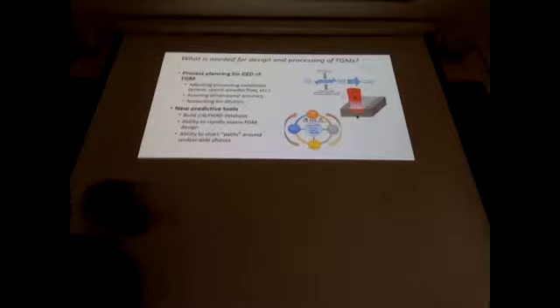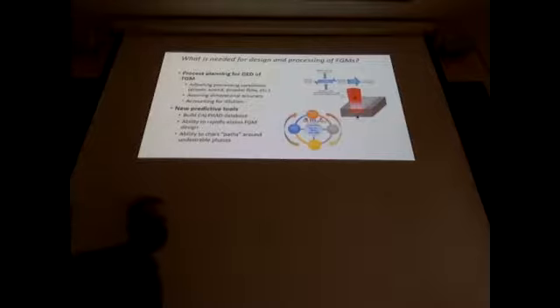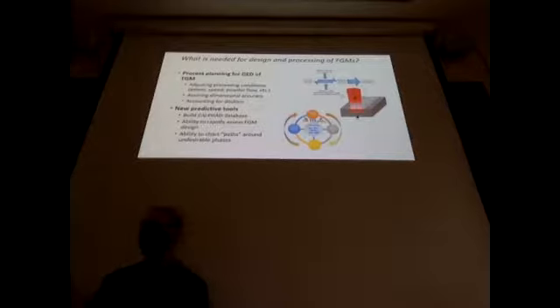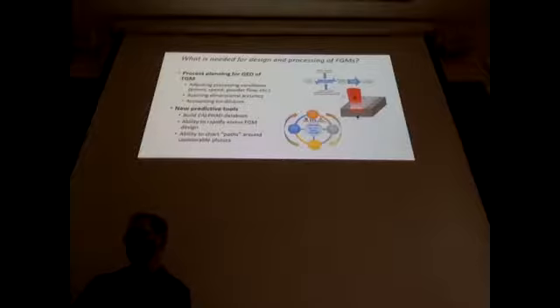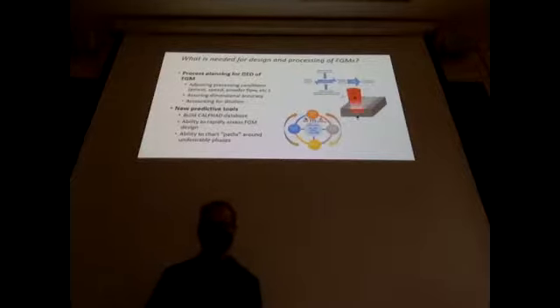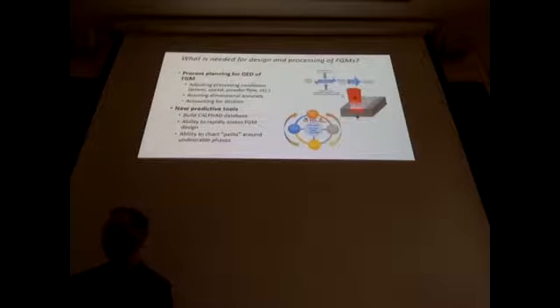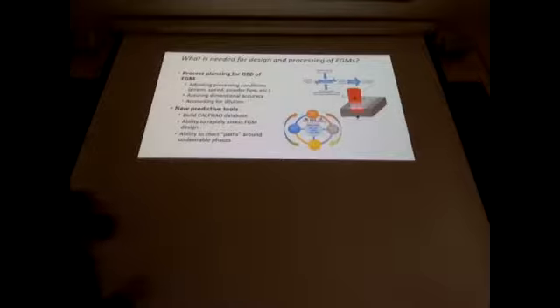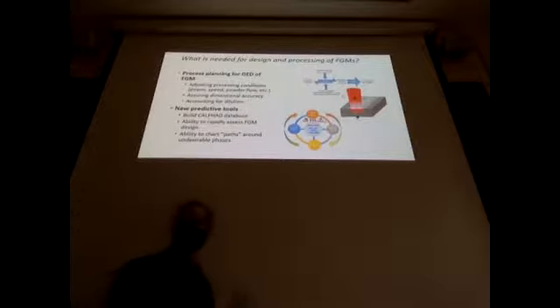And one of the 2 areas that came up that we really felt like we needed was process planning for DED of functionally graded materials. Basically, you're asking to change the material on the fly. And the benefit of additive manufacturing is you can do this layer by layer. You can design where you're putting your material down, and that in turn can design where your grading goes. But in order to do that, you need to make sure that the laser system and the power delivery system is able to compensate for these changing material types. So if you're mixing 2 materials together, like a titanium and a slightly lighter aluminum, or a titanium with a slightly heavier steel or Inconel, you need to be able to adjust for both the power and the feeding rate as well. And that ensures that you're depositing what you want, you're remaining dimensionally stable.